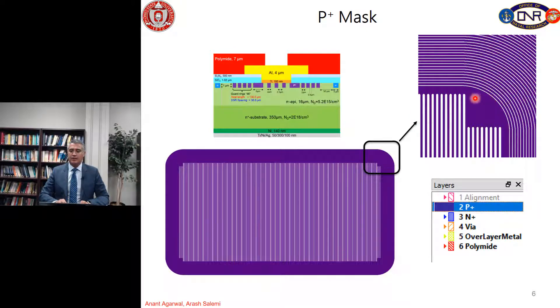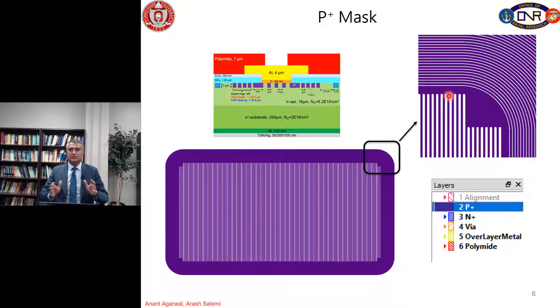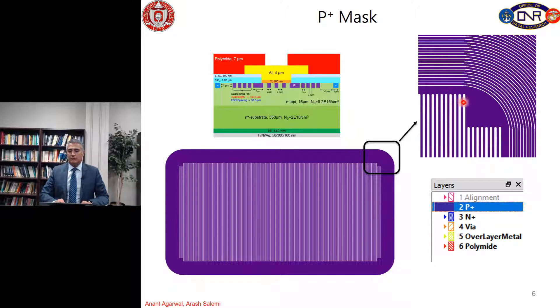We need a wider P+ region for the last P+ in the active area for rounding these corners. I also rounded the ends of the fingers as well. It doesn't matter which cell geometry you're designing — fingers, squares, or hexagons — you need to round the corners. In order to have rounded corners for these fingers, I added extra area at these four corners, and then you can see we have proper rounding for the fingers as well.